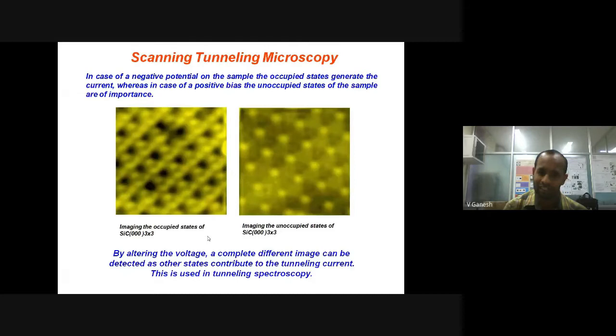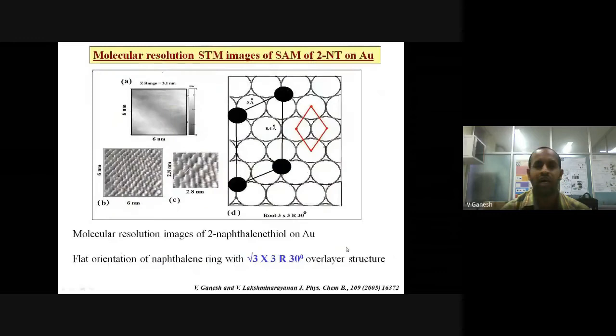You need to scale up. For example, if you scan initially, let's say 10 nanometer by 10 nanometer, and you double the area of scan, the structural features should also be doubled. Instead of getting double the structural features, if you get triple or four times, then that suggests it is an artifact and not a real representation of your sample substrate. By altering the voltage, one can even get a completely different set of images, but we need to understand how the tunneling current works.